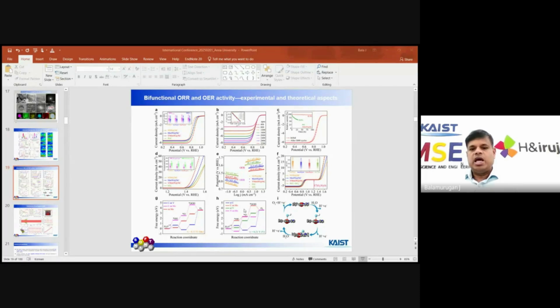And we also do the highly flexible systems like 0 degree, 45, 90 or 180 degree, minus 180. So this confirms that both the upper side and lower side, OER as well as ORR, are maintained in the cell voltage, there is no loss. From this analysis, we confirm that our catalyst, our air cathode, is highly flexible in different bending angles, and we also do the different temperature tolerance ability, minus 20 degree to 80 degree. Then when temperature reduces, the cell voltage is reduced, but not lost much when compared to the other commercial catalyst. I didn't show the commercial one here.